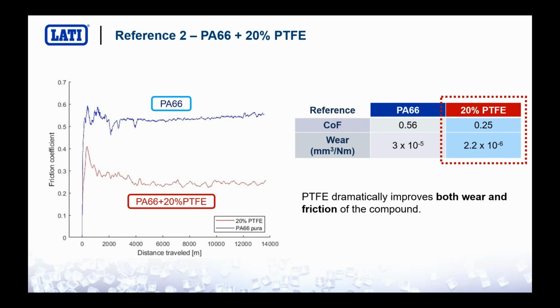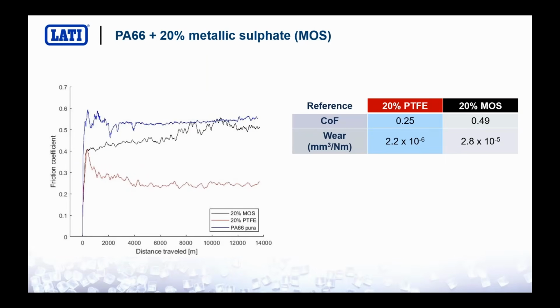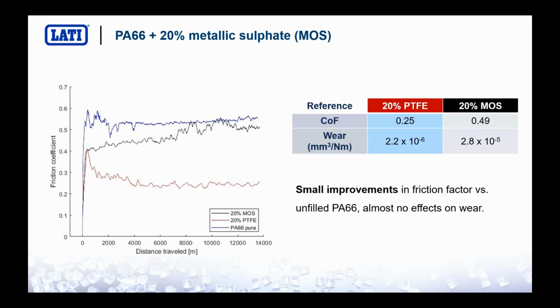Let's start, for example, with some metallic sulfates that we analyzed. As we can see, the tested material is always in black. For what concerned the metallic sulfates, we saw only a small improvement in the friction coefficient, from 0.56 to 0.49, but almost no effect on wear.